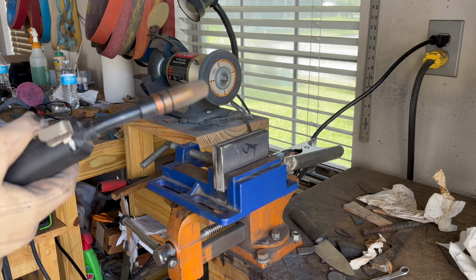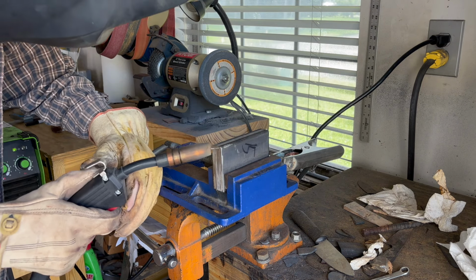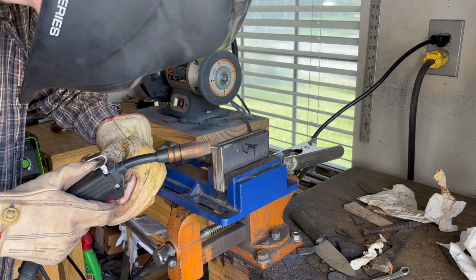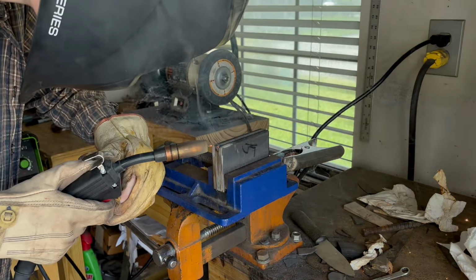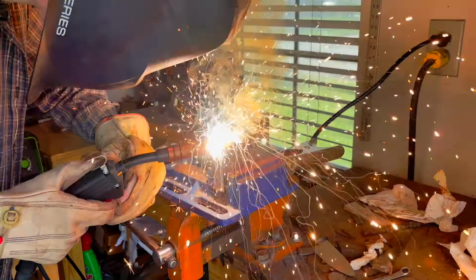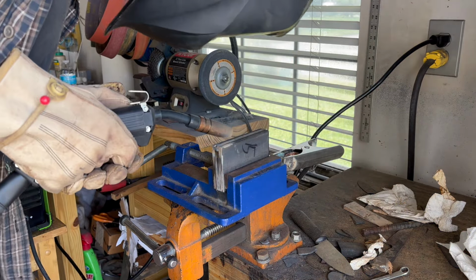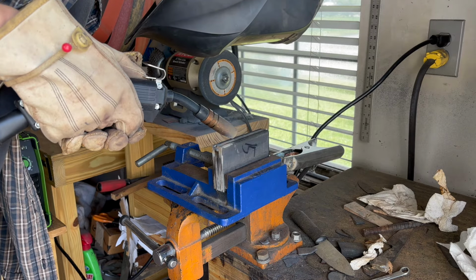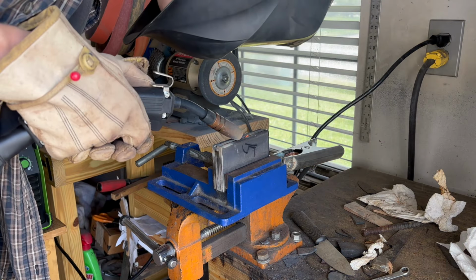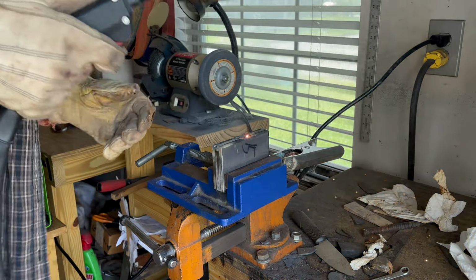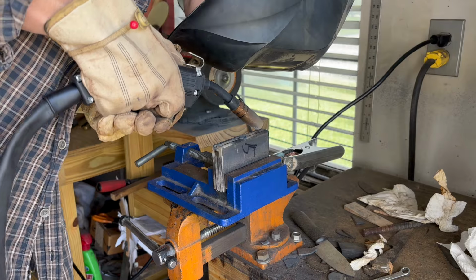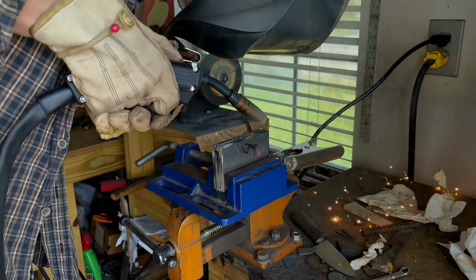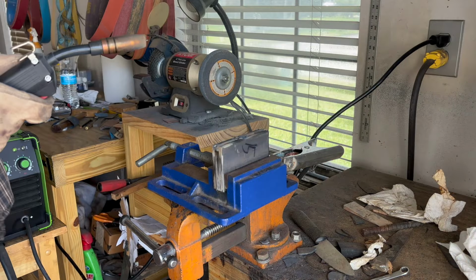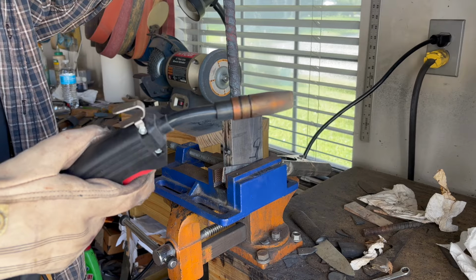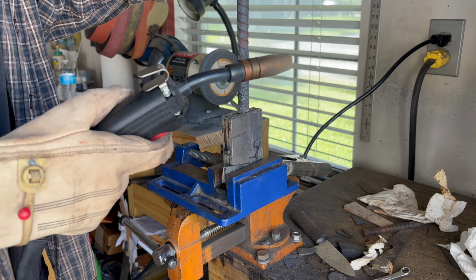What I've started doing is actually using the smallest amount of welding just so I can keep the layers together in the forge. What I found, at least with my cheap flux core welder, is that anywhere where I put some weld bead, it almost always ends up creating a cold shut. So compared to welding all the way around the billet, which I've heard keeps the oxygen out and makes the welds easier, this has actually been much better for me, at least.